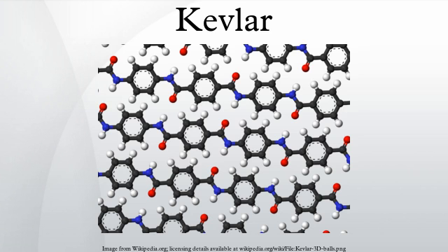Production: Kevlar is synthesized in solution from the monomers 1,4-phenylene diamine and terephthaloyl chloride in a condensation reaction yielding hydrochloric acid as a byproduct. The result has liquid crystalline behavior, and mechanical drawing orients the polymer chains in the fiber's direction. Hexamethylphosphoramide was the solvent initially used for the polymerization, but for safety reasons, DuPont replaced it by a solution of N-methylpyrrolidone and calcium chloride. As this process had been patented by Akzo in the production of Twaron, a patent war ensued.